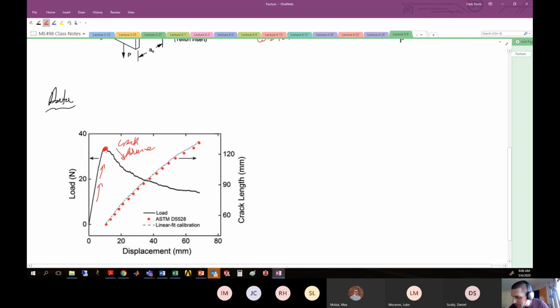And so right when this point occurs, the sample is relieving itself by creating a free surface. And so we're moving down here and we're looking at, all right, what is the current crack length? So that's kind of the right-hand side y-axis here, as we are opening the sample up. Okay, so you can match each one of these 5 millimeters of crack advance with a various load displacement value. So here's my load displacement value for a crack length of there, and you can use all this information to calculate